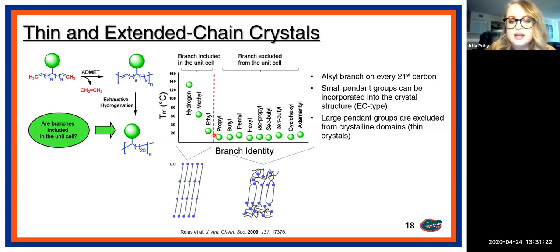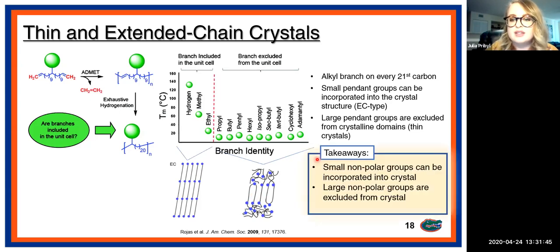And the reason for that is because there's been a transition in the secondary structure from an extended chain structure to a thin crystal structure. And the reason for this is at some size, the functionality is too big to be incorporated into the crystal structure, so it must be excluded from the crystalline domain. So the takeaway from this is that small nonpolar groups can be incorporated into the crystal, and large nonpolar groups are excluded from the crystal. So this is the first part of our design rules that we think about when we're trying to target these different morphologies.